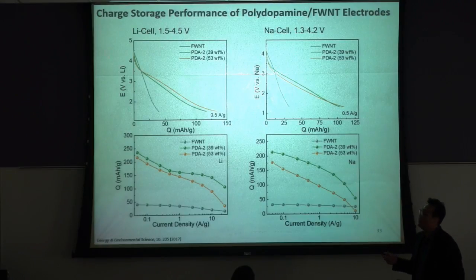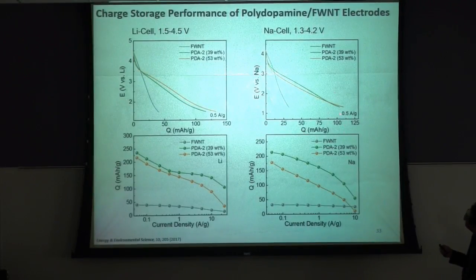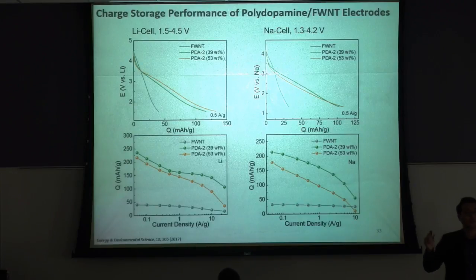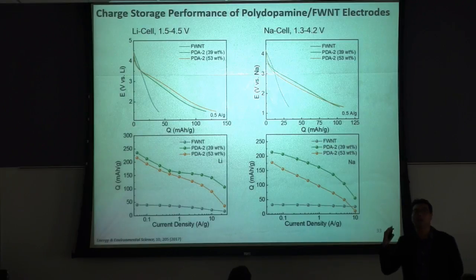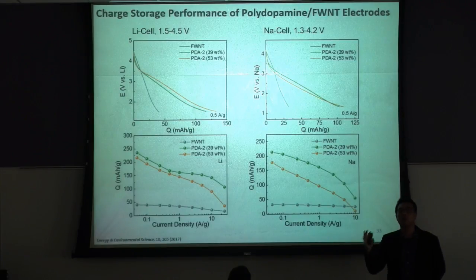So then if we compare discharge profile in lithium cell and sodium cell, this gray one is just pure carbon nanotubes, gives only 40 or 30 milliampere hour per gram in lithium cell and sodium cell. And by incorporating this kind of redox active polydopamine, we can increase the overall capacity over 130 in lithium cell and 115 in sodium cell, right? But this capacity has been calculated based on the total mass of the electrodes, including carbon nanotubes and polydopamine, right?